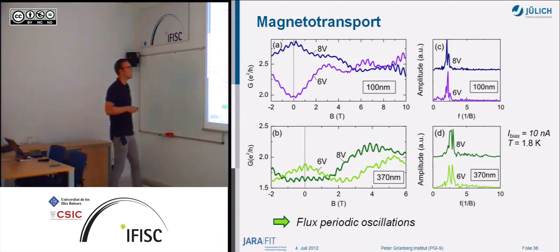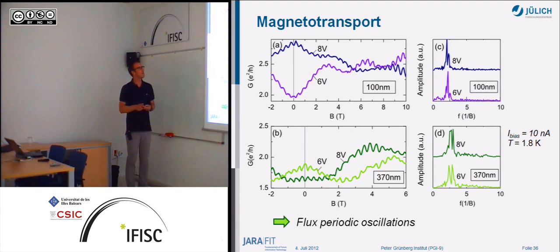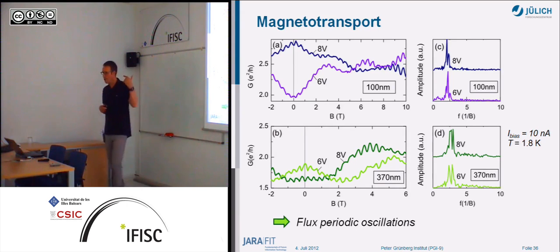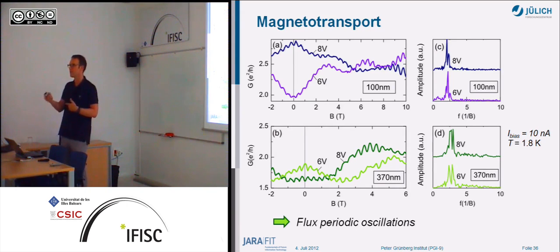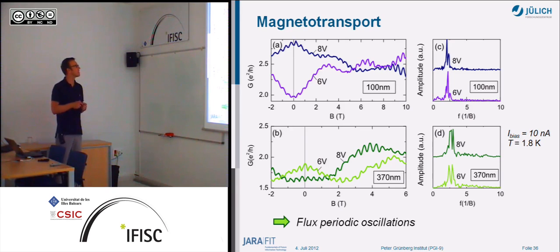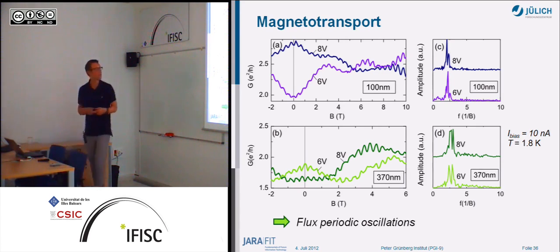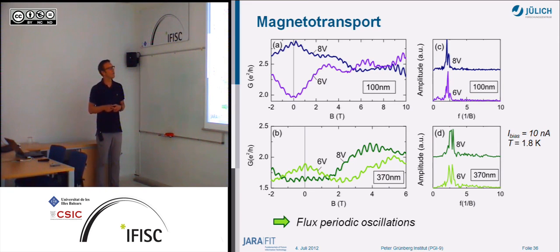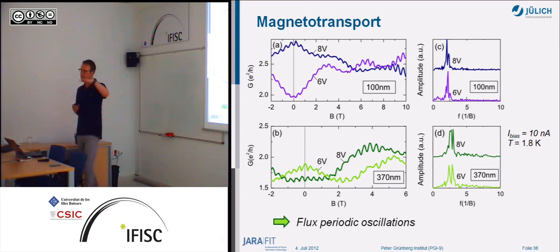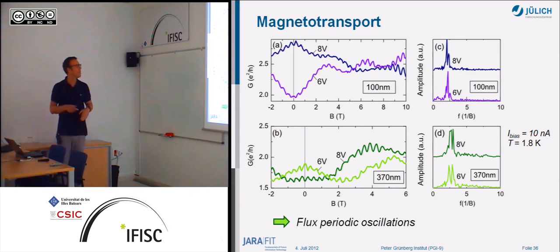And here you see the result. This is the magnetic field, and this is the conductance. This is more or less raw data. We measure the resistance, but this is simply the calculated conductance, with also some universal conductance fluctuations here. But you see immediately that there are some very regular oscillations in the conductance. If you do a Fourier transform, you see, and you can do a backgate measurement to change the electron concentration, that no matter what gate voltage you apply, you always get a peak at a certain position.